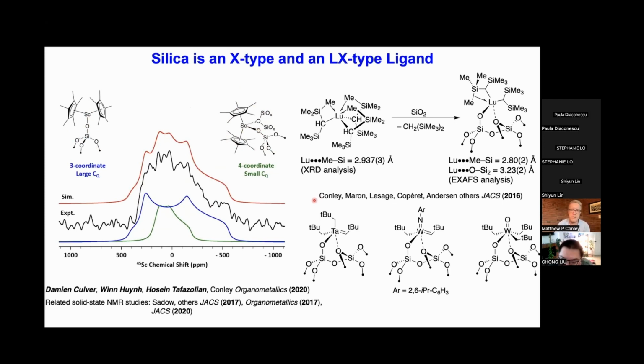So one that came up as part of my postdoc in Christoph's group, in collaboration with Laurent Maron, Anne Lesage, and the late Dick Anderson, was the reaction of this organolutetium compound with silica 700. These organolutetium compounds are interesting because they contain nearby secondary interactions with the proximal trimethylsilyl fragments. So these you can think of as a bridging silicon methyl lutetium group. And these distances, when you graft onto silica, contract quite significantly.